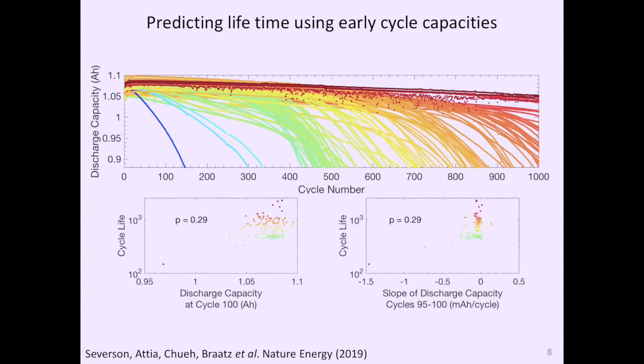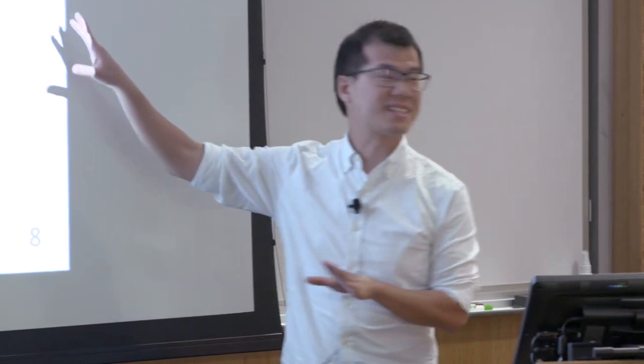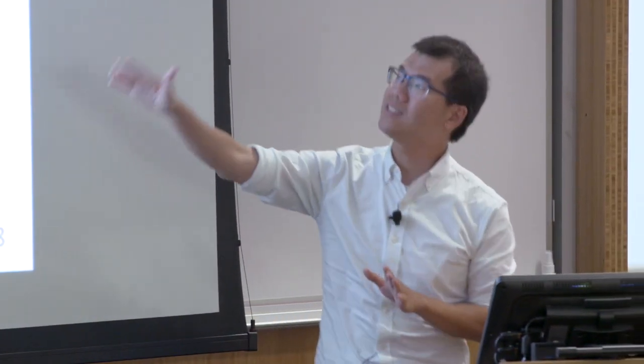And if I do a rigorous statistical analysis, I can see that the cycle life has very weak correlation with the performance at the 100th cycle. And also, if you look at the slopes of the degradation rate, there's also very weak correlation, almost a straight line, which means there's no correlation in this case. So that means whatever the degradation mechanism is, the thing we're trying to predict is very silent. Okay, so it doesn't show up until it shows up. So this is a very challenging problem.